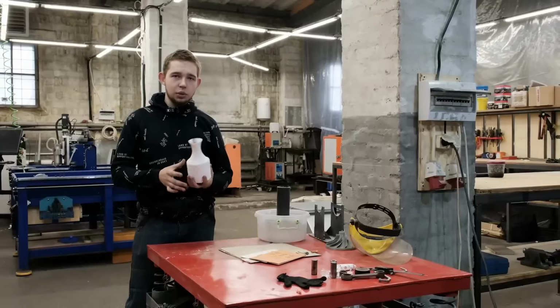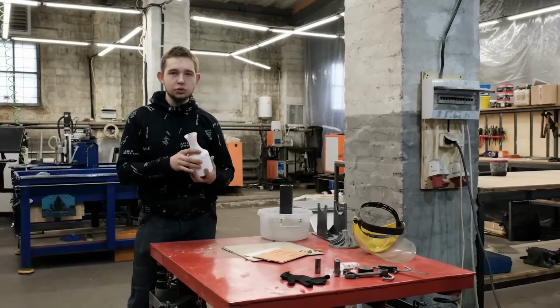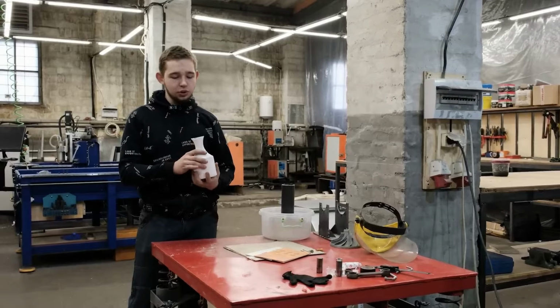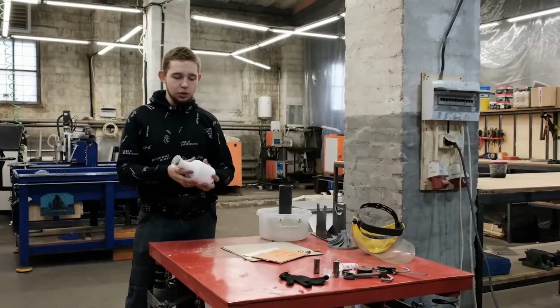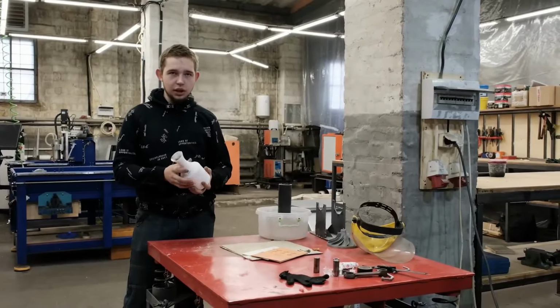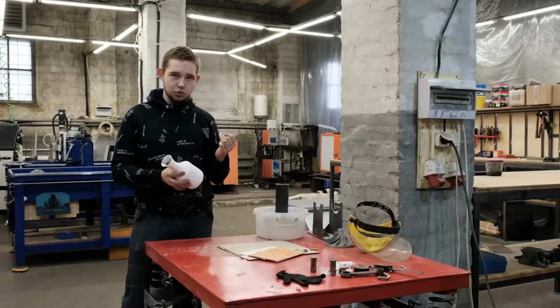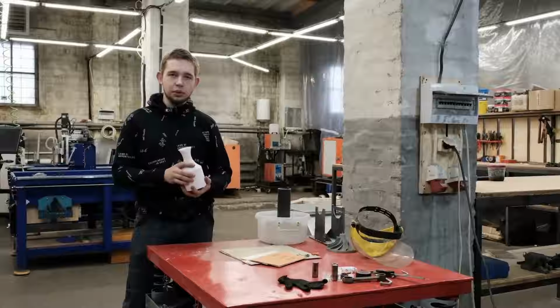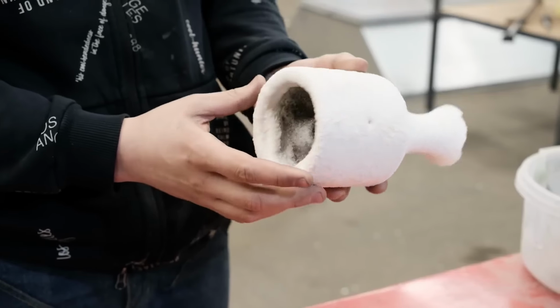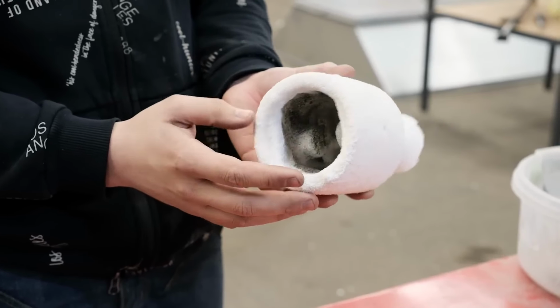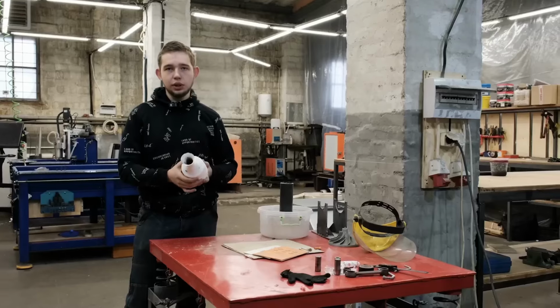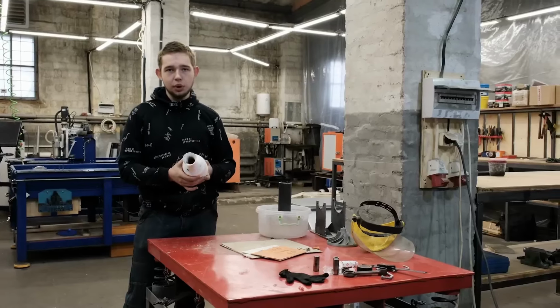So we burned our plastic in a muffle, the mold was fired, and now we have a ready-made ceramic shell into which we can pour metal. Now we carefully cover it with sand, then put the muffle back in to heat up to the proper casting temperature. After that, we take it out and pour in the molten aluminum. This is more or less how it looks. The shell completely replicates the shape of the plastic part.